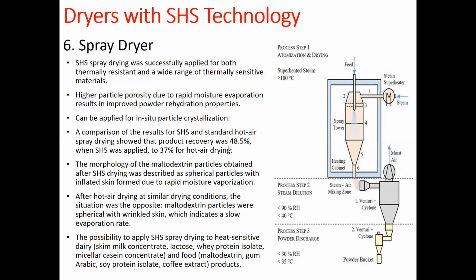A comparison between spray dryer with SHS and standard hot air showed the product recovery is about 49%, but for the hot air dryer it is only about 37%. The morphology of the maltodextrin obtained with the superheated steam spray dryer was described as spherical particles with inflated skin. So it looks very nice, a very rounded shape, due to rapid moisture vaporization. But if you use hot air drying, the maltodextrin is the opposite, where you can see wrinkled surfaces, which indicates a slow evaporation rate.